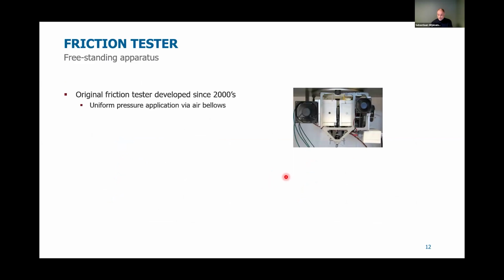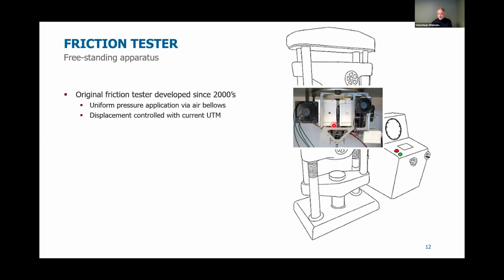Now we talk about friction testing. Here you see the original friction tester. It, in fact, is two pressure bellows that push heated platens against the ply-ply configuration, and you place this into a tensile tester and then pull the ply from the two plies, and it's all displacement controlled with our universal tensile testing machine. It's tedious work, need some operator skill here, and with, say, an outlook on further and more characterization work and